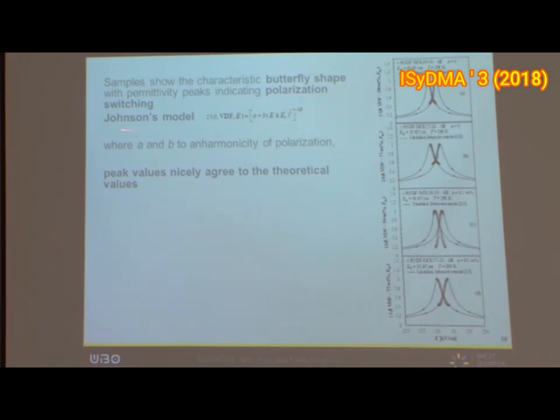And one way, you apply this Johnson model, depending on two parameters, A and B, depending on the anharmonicity of your model, so you can have a very good fit. So this measurement nicely agrees with the theoretical curve, and it can be interpreted with the standard Johnson model, which each of you can use for this kind of sample.